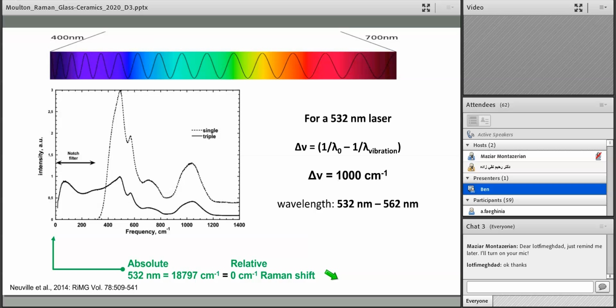For those of you who are totally new to Raman, and for those who want a little review, we look at relative wave numbers. Here is a spectrum. On the left side of your screen, we have some intensity that we record on our detector, and we have some scale of frequency. This is reported in frequency sometimes, it's reported in wave numbers, in inverse centimeters, or as Raman shift. And it's important to just remember that this is a shift in wave numbers, inverse centimeters, relative to our incident laser light. So we can describe the incident laser light. For instance, if we have a green laser, a 532 laser, you can do the simple math to convert nanometers to inverse centimeters, and you'll get this value here,